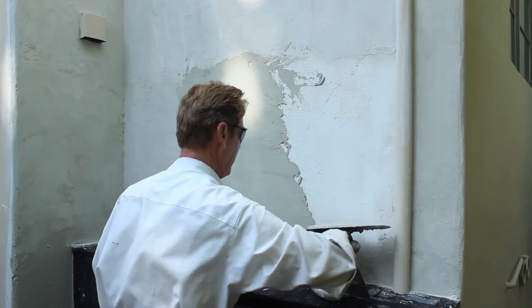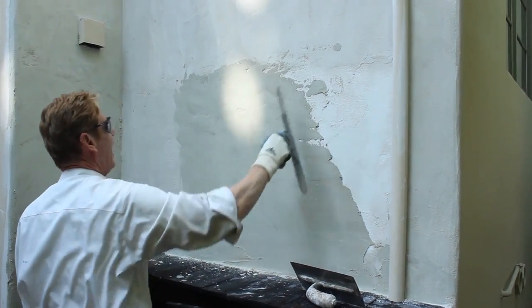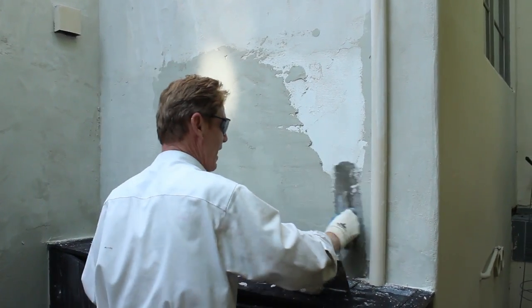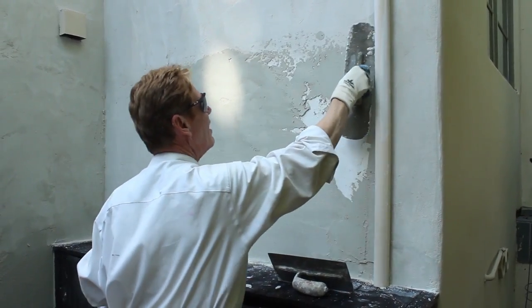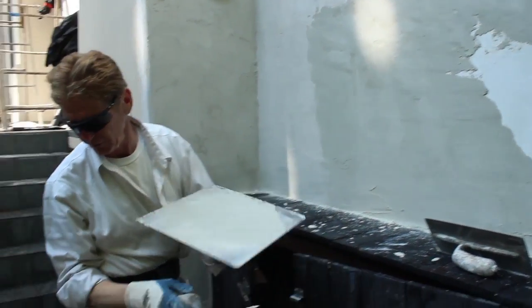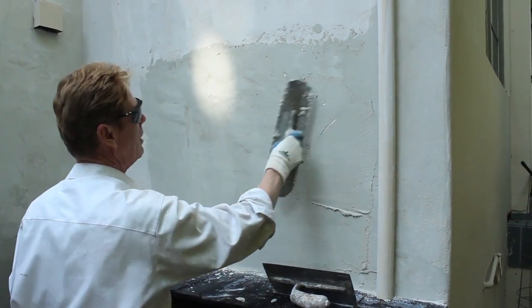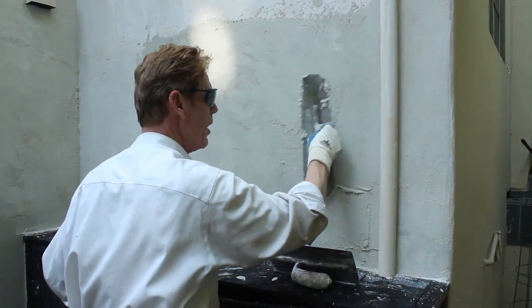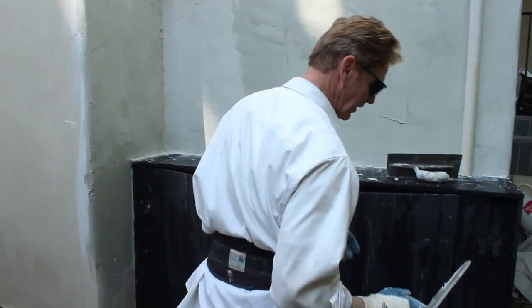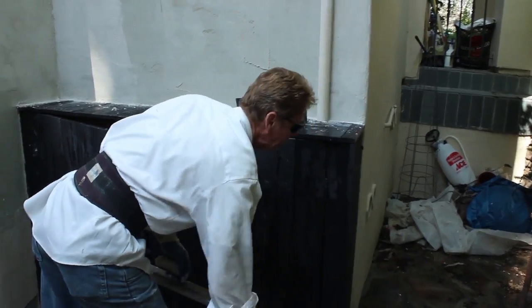It's very similar to the veneer finishes - I show how to do veneer finishes in quite a few other videos, and we also show how to do Santa Barbara smooth mission finish. But that's not what this video is about. This is just about loose stucco and some of the reasons why stucco can become loose. Usually it's a matter of absorption - whether or not it has a bonding agent or you're going over a brown coat. Absorption is everything. You can't have dust, moss, or dirt on it because nothing adheres to a dusty surface.